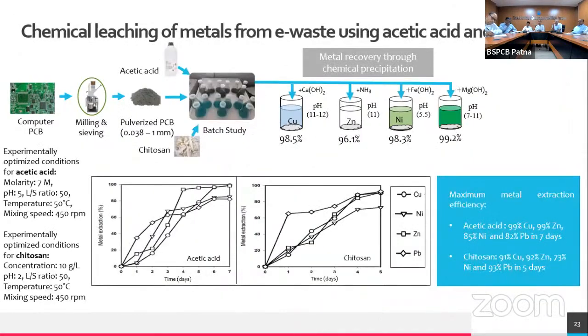Followed by this, we have also tried with another organic acid, let us say acetic acid, which is commonly used, and also we have used a biopolymer. I'm sure you have heard about chitosan, which is generally present in the crust of the shrimp. From that we can have this biopolymer, and it also has chelating property. Here also we have performed the experiment with computer printed circuit boards, subjected to milling operations, using either acetic acid or chitosan as biopolymer.